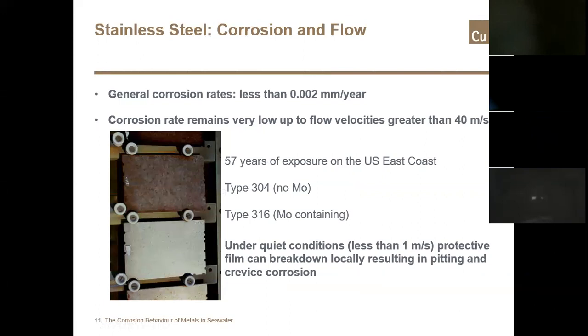The slides here show some 304 stainless, which is the top sample that's been exposed, and below that is some 316 stainless, which has got molybdenum content in it. With the 304, the structure is still quite usable, especially after 57 years of exposure. It has got some signs of rust, but it's not disastrous. But more impressively, the 316, containing the molybdenum, has resisted light corrosion. So as long as we remain with a constant flow and plenty of oxygen, the stainless steels are capable of lasting for a significant amount of time.